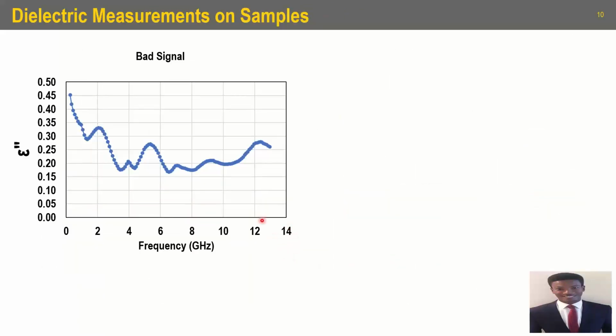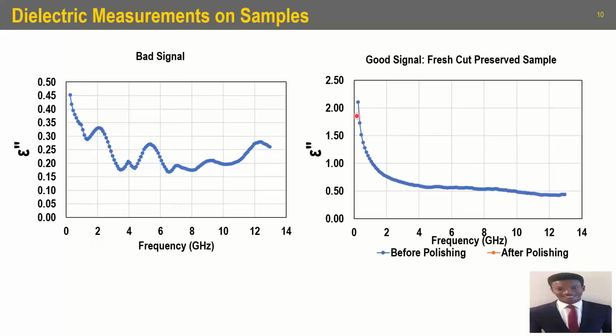So on this slide, I show you an example of what a bad signal looks like on our dielectric loss measurements on a sample, and what a good signal looks like on a fresh cut preserved sample. You see that a good signal, before polishing and after polishing, shows a good exponential decline for the dielectric loss as a function of frequency, and the magnitude of the dielectric loss is pretty much higher compared to the one for the bad signal. So this is our QA/QC in order to be sure that the data we are collecting is good enough.